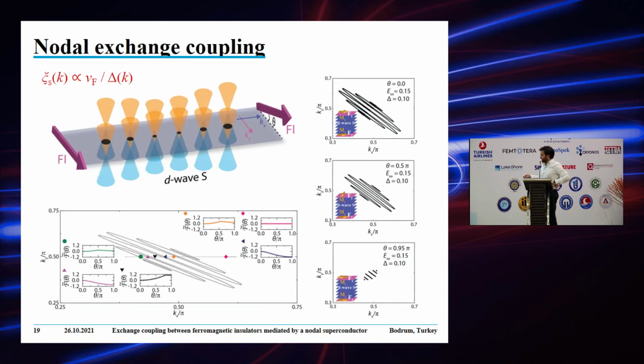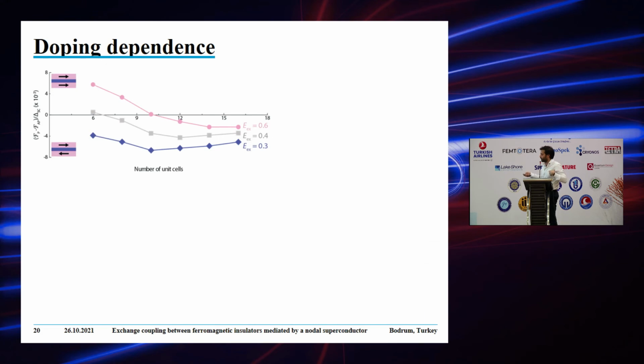Now, the point, very briefly, is that when a superconductor becomes thick, the energy of the superconducting condensate is basically favoring this anti-parallel alignment, whereas when it becomes thin, you basically have a lot of quasi-particles in the system that are carrying the spin polarization from one ferromagnet to the other, and therefore the parallel alignment is favored. So this is, in very few words, what's happening.